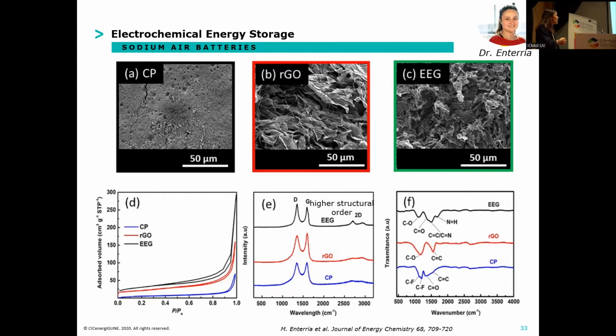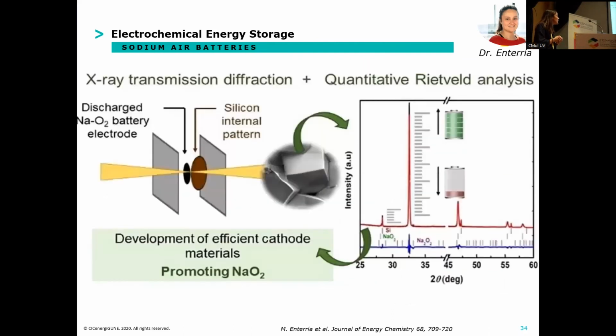But for this work, what we did is to use X-ray diffraction to quantify the efficiency of this discharge product. So what we did is discharge a sodium oxygen battery electrode, and then with an internal reference, we can quantify how much sodium superoxide we have in our cell, depending on the cathode we were using.